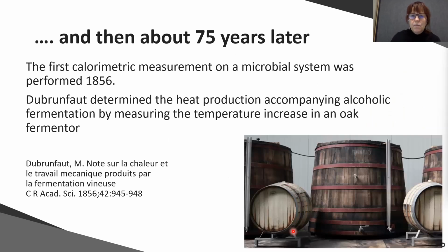Then about 75 years later, the first calorimetric measurements on a microbial system were performed in 1856, where the heat production accompanying alcoholic fermentation was measured by measuring the temperature increase in an oak fermenter. So this is a little in analogy with what I showed, the coffee cup calorimeter from the beginning, where you have an isolated calorimeter container and you measure temperature increase.